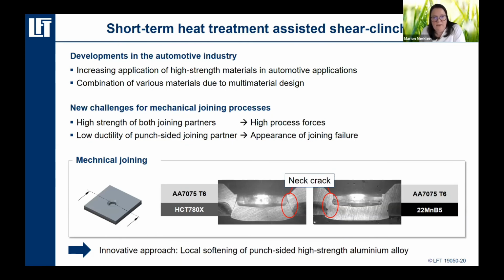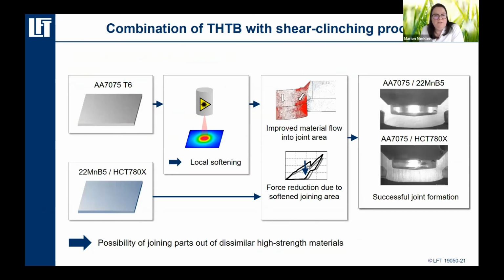And so we said, okay, if we have the good results from two other applications, why not transfer the results to that? And so what we did was, again, an analysis of how we have to locally soften the material in order to improve the material flow, and the effect was exactly as we expected. Again, we can temporarily soften the material, we can improve the material flow, increase the ductility a little bit, so we can come to a successful joining. And so we showed for the first time the possibility of joining parts made of dissimilar high-strength materials, especially using the steels and the high-strength aluminum alloys.